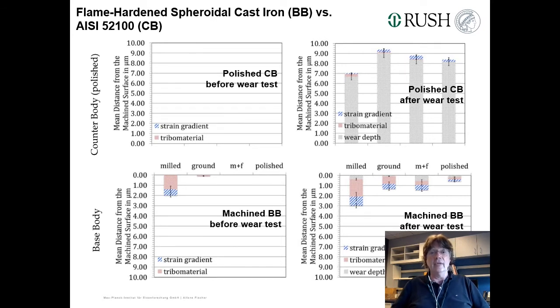I think it's because down here, after flame hardening, the cast iron had compressive residual stresses. Again, a question pops up. The compressive residual stresses are roughly 800 megapascal, while the real contact stresses, which have been simulated here by Daniel Stickel in a parallel PhD thesis, are 8 gigapascal. The question is, how can 10% of the real loading in the real contact area have that effect